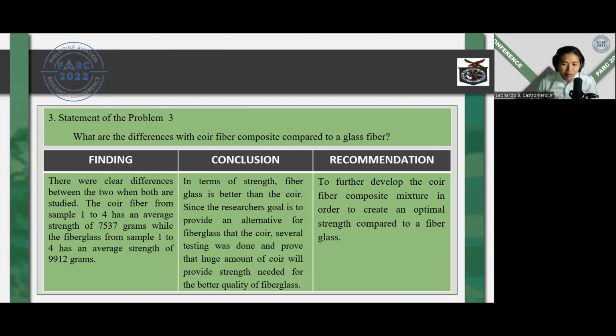Statement of the problem number 3. What are the differences of coir fiber composite compared to glass fiber? Finding. There were clear differences between the two when both are studied. The coir fiber from sample 1 to 4 has an average strength of 7,537 grams, while the fiberglass from sample 1 to 4 has an average strength of 9,912 grams. Based on the results, fiberglass has much more strength compared to coir fiber.